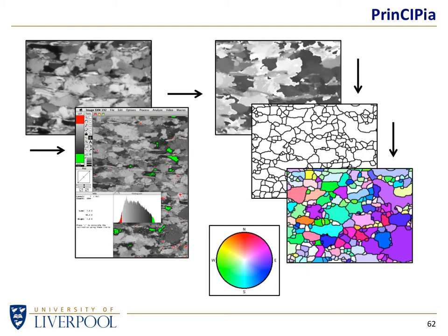And so each of these, we've now quantified exactly which way they're pointing. We can see perhaps there are 2 grains which are very similar colors, but that tells us that they're oriented in similar but not the same direction. One of those grains has the atoms pointing this way, the other one has the atoms pointing in a similar but not quite the same direction, because they are similar but not quite the same colors.